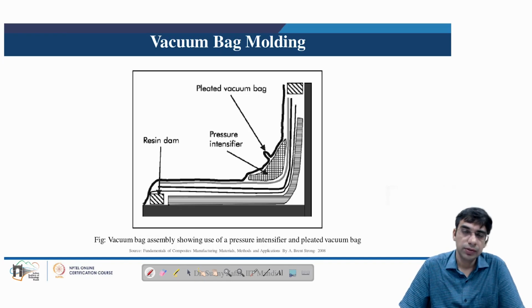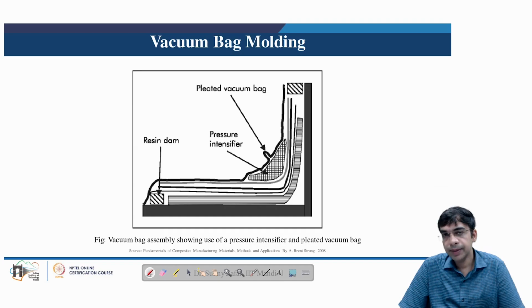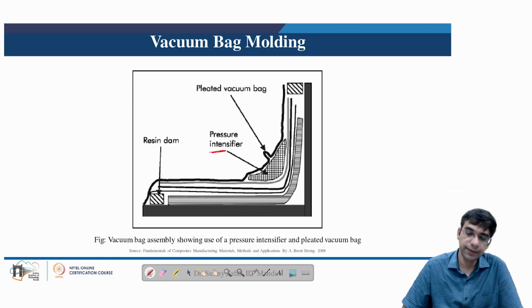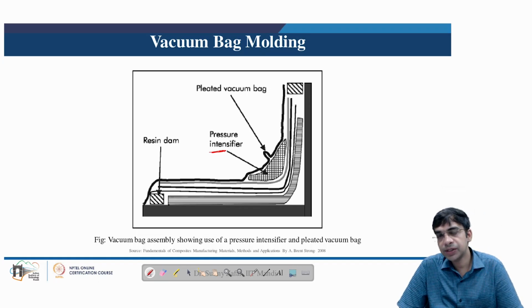In many situations, in this mold there may be certain tight corners wherein the resin may not flow very easily, and because of which there may be some wrinkling on the vacuum bag. This type of situation may lead to development of some entrapped air, which may manifest itself in the form of some porosity or micropores in the cured part. So a pressure intensifier is used here. This pressure intensifier helps to uniformly distribute the pressure in the tight corner, therefore avoiding any unfilled regions in the composite part.